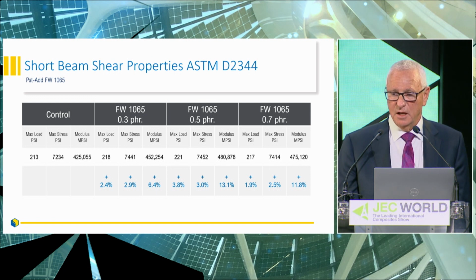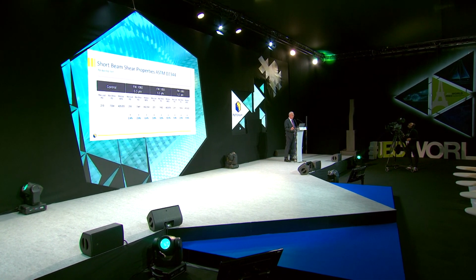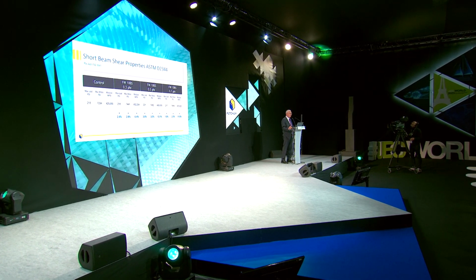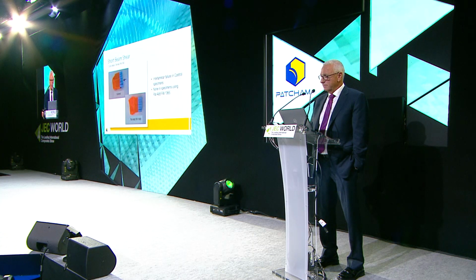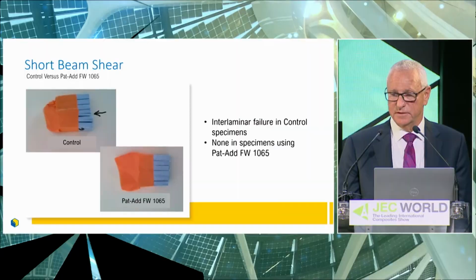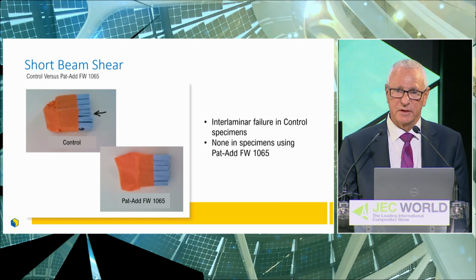And short beam shear, not nearly as dramatic as we saw on the contact laminates, but still significant: you got a 3.8% increase in the maximum load on the short beam shear, or interlaminar strength, just by putting in 0.5 parts per 100 of an additive. Other interesting thing here, those are all the control specimens, and you can see several of the control ones failed interlaminarly, they did break up, whereas the ones where we used the additive didn't fail interlaminarly, they failed at the bottom side, the deflection side.